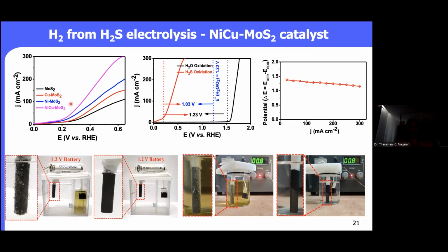And compared to the nickel molybdenum sulfide and also just the copper molybdenum single metal catalyst here, the activity is quite low, and also the molybdenum sulfide is quite low compared to this material. Now to confirm whether this is due to the sulfur oxidation reaction or not, we have done control experiments, that means the experiments in the absence of H2S. When we have done without the H2S, you can see this black color graph here. So the current starts to increase at 1.52 volt. That means this curve is due to the oxygen evolution reaction, and it is confirming that this red color one is due to the presence of the H2S, that means sulfur oxidation reaction.